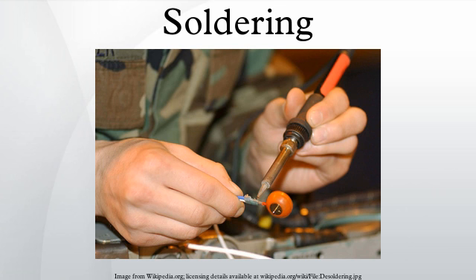For attachment of electronic components to a PCB, proper selection and use of flux helps prevent oxidation during soldering, which is essential for good wetting and heat transfer. The soldering iron tip must be clean and pre-tinned with solder to ensure rapid heat transfer. Components which dissipate large amounts of heat during operation are sometimes elevated above the PCB to avoid PCB overheating. After inserting a through-hole mounted component, the excess lead is cut off, leaving a length of about the radius of the pad. Plastic or metal mounting clips or holders may be used with large devices to aid heat dissipation and reduce joint stresses. A heatsink may be used on the leads of heat-sensitive components to reduce heat transfer to the component. This is especially applicable to germanium parts.